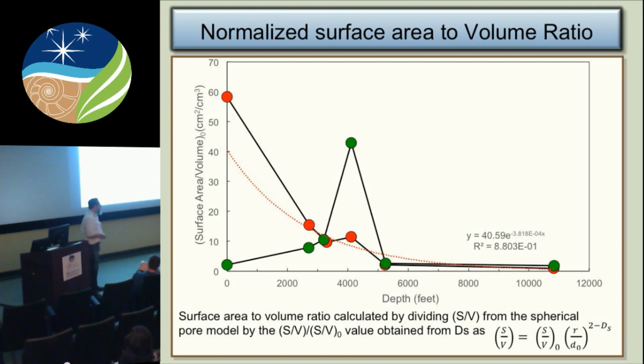So if we want to see what's happening with depth, we put this here, but this is really what the pattern is. You can see that in general, surface area to volume ratio is decreasing in these samples. So we're getting less reactivity, less ability for reaction in any given sandstone. However, at least for one, the difference between red and green, by the way, is simply for all those 30 sandstones, one looks at the samples with the highest porosity at each depth. The other one's the samples with the lowest porosity at each depth.